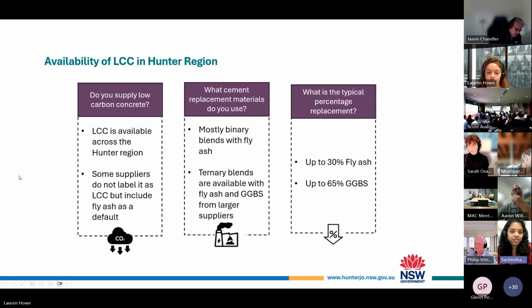Yep. So moving on to the questions, from these 15 suppliers we have engaged for low carbon concrete, we focused on getting information on fly ash and slag, or GGBS, which refers to ground granulated blast furnace slag. Most of the feedback we got was positive. They do have low carbon concrete in the Hunter region, and we have received 2 feedbacks from 2 smaller suppliers saying that they don't provide low carbon concrete. Also, we got to know from most of the suppliers that they already include a percentage of fly ash in their mixes as business as usual, like Lauren mentioned earlier. In that case, they don't specifically name these mixes as low carbon concrete, but they do have a percentage replacement of fly ash in their mixes already.